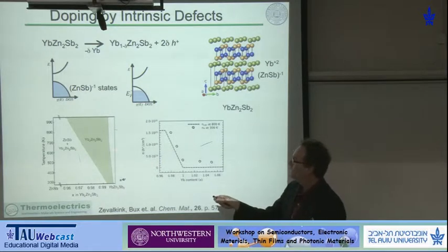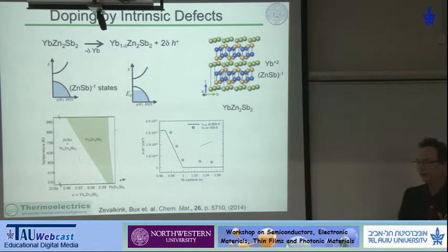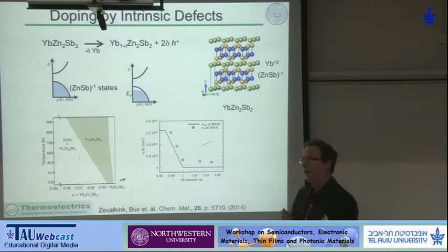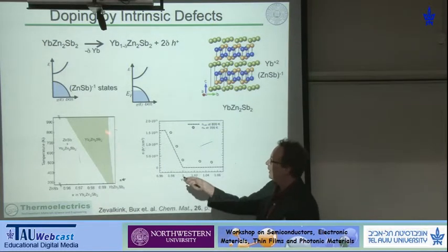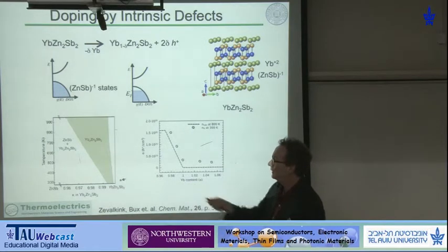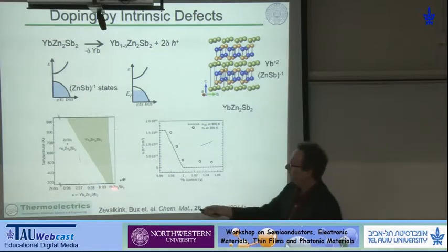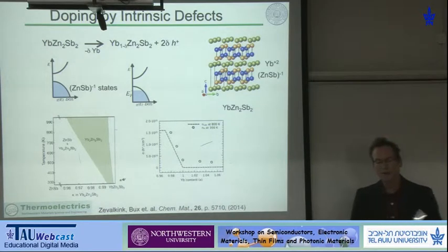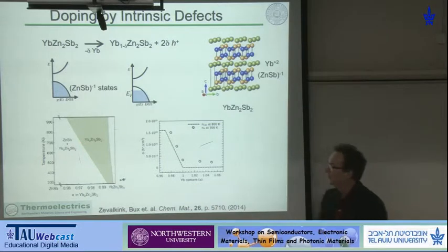And what we've noticed is that this defect concentration is variable, and we can draw that in terms of a phase diagram like we did with the lead telluride, where the shaded region is the allowed range of ytterbium content, and all of this shaded region lives to the left of the pure compound, meaning that this material is always p-type, and the carrier concentration can be adjusted only within the shaded region.